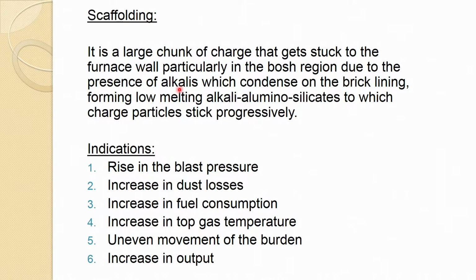And because when you are charging the furnace, fines are also generated, and when this material becomes quite soft, these fines and other things can accumulate on this, and then it progressively increases in size. So, the presence of alkali is the main reason for accretion development on this brick lining.